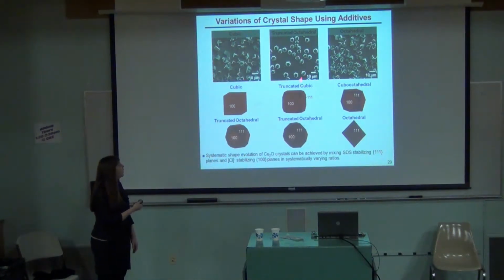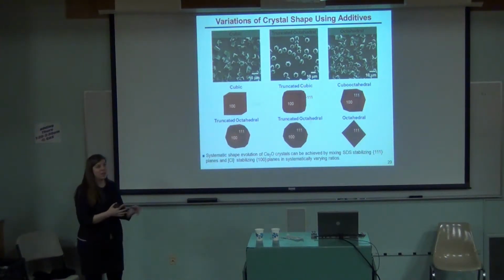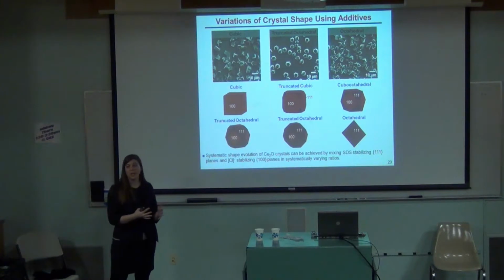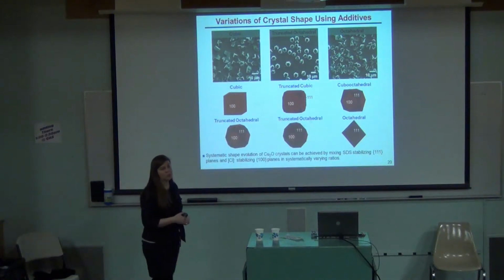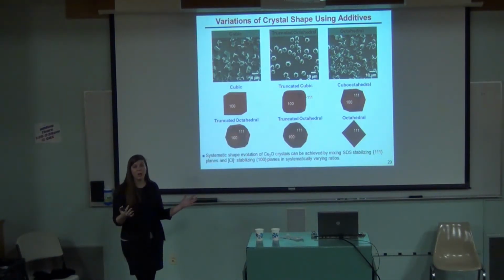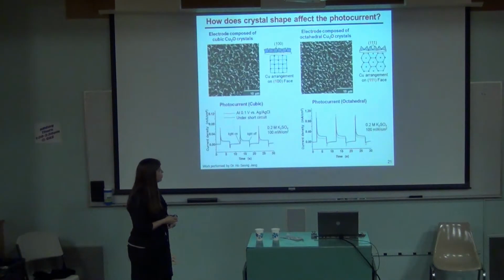We can make cubic, we can make truncated cubic, we can make cube octahedral, we can make truncated octahedral, we can make any shape and variation of the 111 and the 100, and we can also throw in a few other like 110, which isn't shown in this picture. The only difference between all of these is how much of these extra additives we put in. So how much surfactant and how much chloride we put in, because those stabilize different faces.